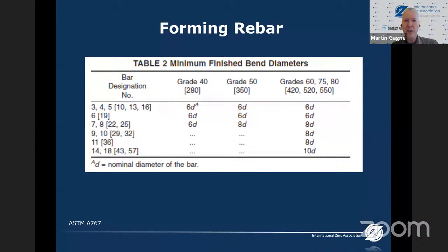I talked about forming rebar. This is for avoiding any strain age embrittlement in the galvanizing kettle. So the bar designation number on the left-hand side, 3, 4, and 5, this is 10, 13, and 16 millimeter diameter bars. So we can see the bar number and the corresponding millimeter diameters in brackets. But we can see for all of the grades and most of the bar sizes, we have to have 6 times the diameter of the bar as a bend diameter to avoid any strain age embrittlement effects. And for the larger bar sizes, we go up to 8 times the diameter and even 10 times the diameter at the higher strength steels.